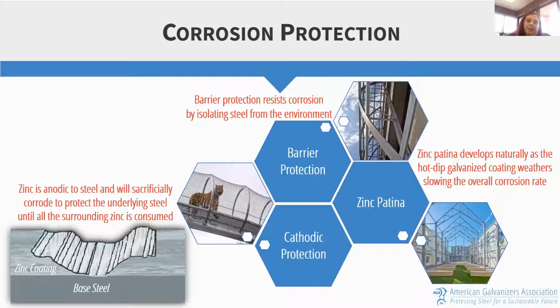But the real longevity of galvanizing comes into play with what's known as the zinc patina. This is something that develops naturally as galvanized steel is exposed to wet and dry cycles in the environment. It produces a series of byproducts on the surface, zinc oxide, zinc hydroxide, and zinc carbonate, which will slow down the overall corrosion rate to about 1/30th the rate of steel in the same environment.